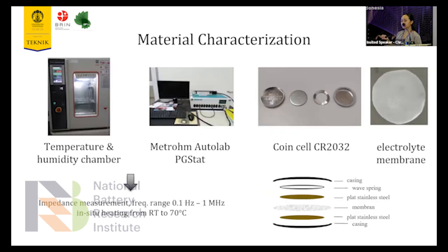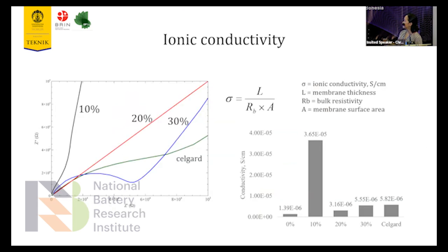This is the material characterization. So for the electrochemical characterization, we use temperature and humidity chamber for temperature variations. And we use potentiostat to measure the impedance and to further calculate the ionic conductivity. We use the coin cell CR2032 and we put our electrolyte membrane sandwiched between two stainless steel plates. Using this formula, we calculate the ionic conductivity.